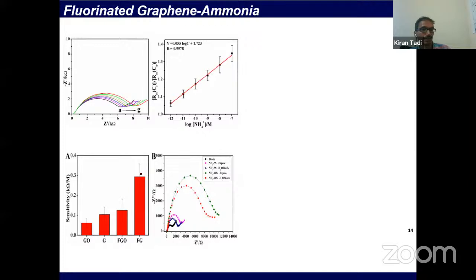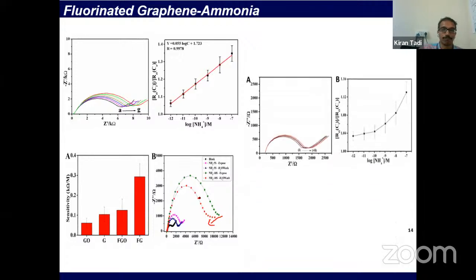As for reproducibility, I can't say it is 100% reproducible, but the impedance does come back again when we wash with water, to some extent, around 40 to 50%, as it detaches again from the surface of this sensor.